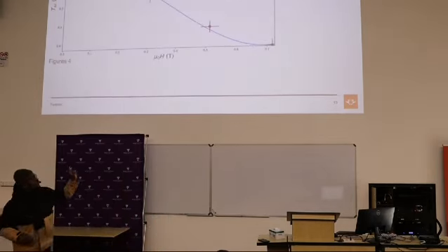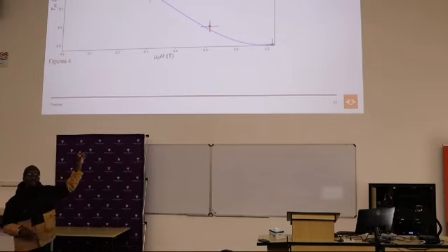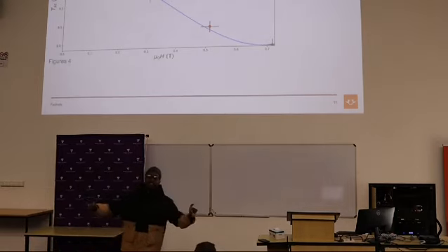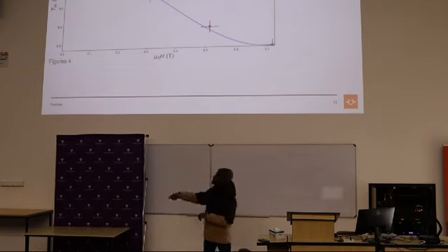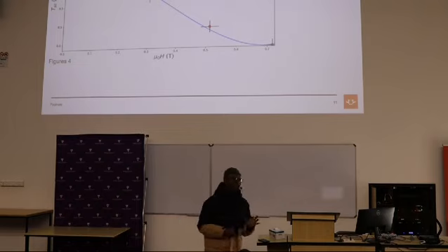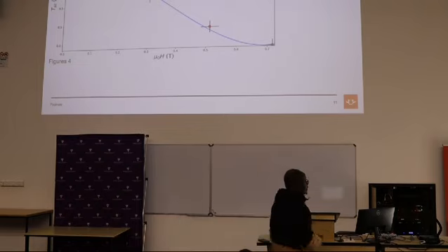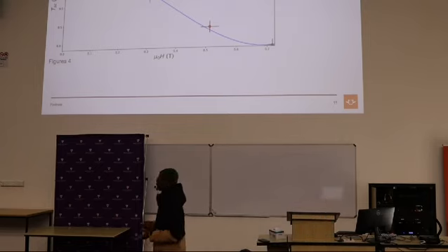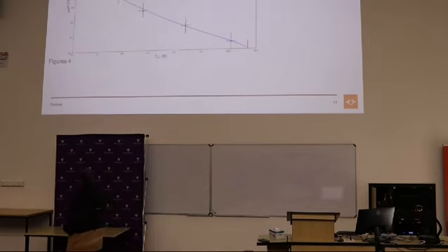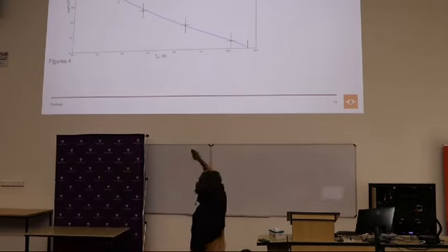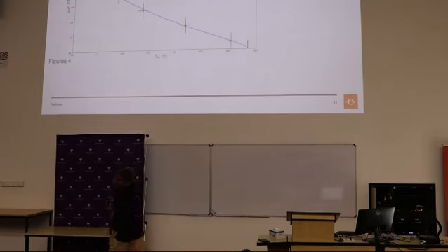Now, from that data, we can then also try to find out what is the critical magnetic field in terms of the superconducting transitions. Since we're changing the applied magnetic field, on our x-axis we have that, and on our y-axis we've got what was changing as a result of that, which is the superconducting transitions. However, for us to correctly fit that equation there, we have to go to what the Ginzburg-Landau theory predicts. And from that, we have to change the graph axes such that the y-axis becomes the applied field and the superconducting transition is over there. And from this, we can then extrapolate the upper critical field for this material that we're dealing with.